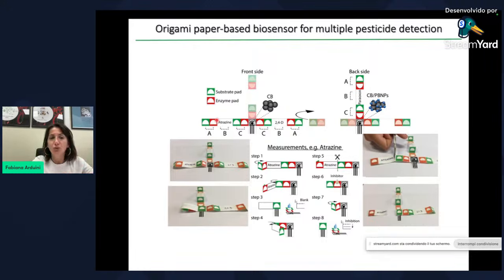I would like to show you, for example, the concept in the case of atrazine. For the first measurement, we fold the first couple of pads close to the electrode surface, add distilled water, this is the configuration, and we make the measurement. For the measurement of the sample, we cut this part and add the sample to the enzyme pad in order to have the reaction between, again, enzyme and inhibitor present in the sample. And after, we fold again on the same electrode this couple of pads and add distilled water in order to detect the residual enzymatic activity.